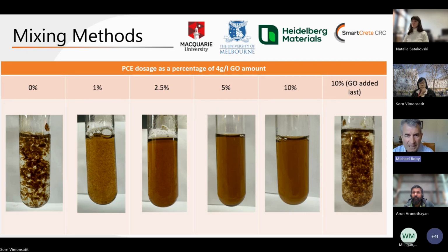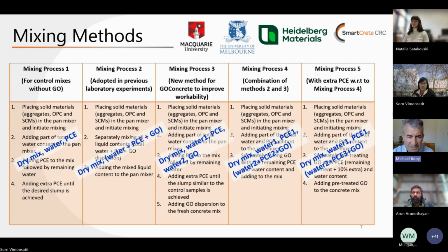I think what we were seeing when we got workability right is we were seeing inconsistent results in 28-day strength improvement, and we believe it was down to insufficient dispersion of the graphene oxide. So I think the aim of the game, in terms of getting consistent strength improvement results, is all about getting the dispersion right. So it really becomes a game about finding what sort of chemistry is going to do the job. And I must say, we didn't really get to that point during this one-year project. We got some results between 5 and 25% strength improvement, but we weren't able to achieve that consistently. So I think there's a huge potential here, but we really need to take it a little bit further and figure out what dispersion agents will get the consistent results.